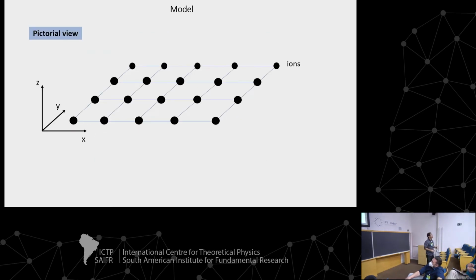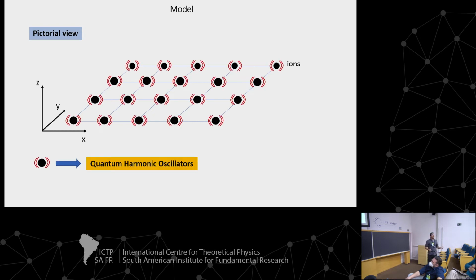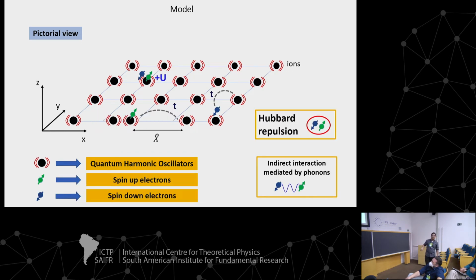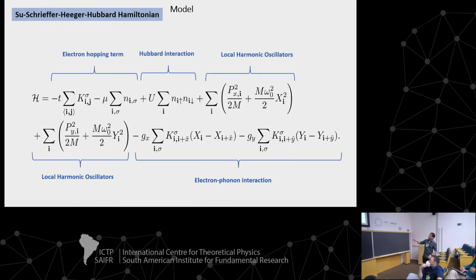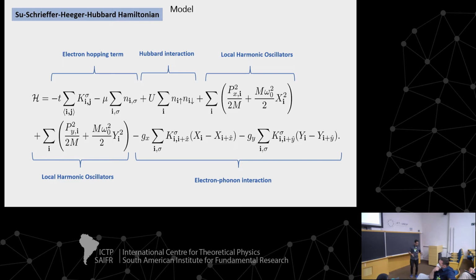The other one is, again, let's come back to the lattice, put phonons here, but the phonon can instead just change the local chemical potential. The phonon can modulate the hopping. And if the phonon modulates the hopping, for instance, you have oscillations that put the atoms closer, the hopping is stronger here. If they put the atoms far away, the hopping is weaker here. So this kind of problem, again with the Hubbard interaction, that modulates the hopping, is called the Su-Schrieffer-Heeger model, the SSH model, in which the electron-phonon coupling modulates the kinetic term. This K here is the kinetic term. So in my talk, I will discuss these two models, the Hubbard-Holstein model and the Hubbard-SSH model. Mostly the first one. For the latter, I have just some preliminary results.